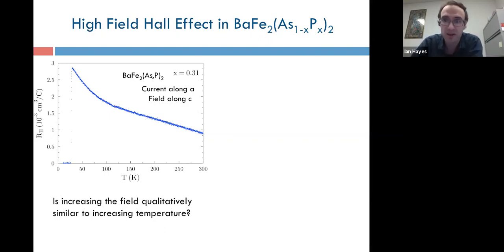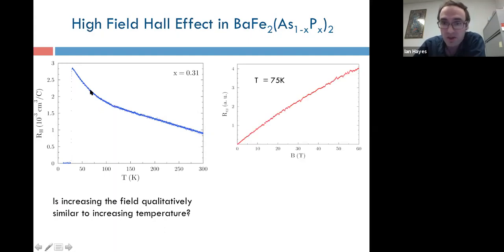That'll be the same configuration for all this data. Now, looking at the temperature dependence here, there's temperature dependence all the way up to 300 Kelvin, but especially at low temperatures, you start to see a sharp upturn that is reminiscent of what I just showed you in the cuprates and in some heavy fermion compounds. And so the question we'd like to ask is, is there any distinctive field dependence in that region?